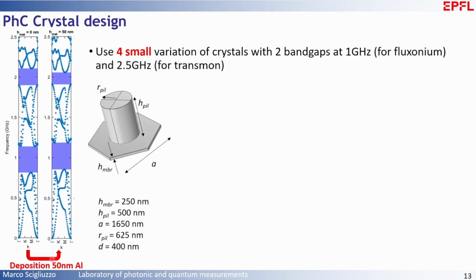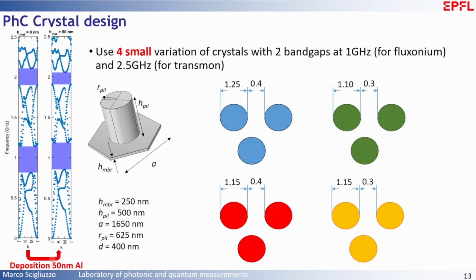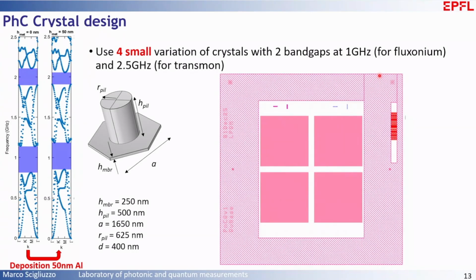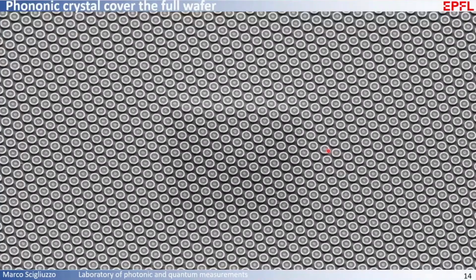So for this we can use optical lithography. You can see the diameter of the pillar is 1.2 micron wide, with around 300 or 400 nanometer separation, and we have the luck to have deep UV. Basically, with a big mask like this, a 6-inch quartz mask for the UV, we are able to pattern the full 4-inch wafer in about 10 minutes.